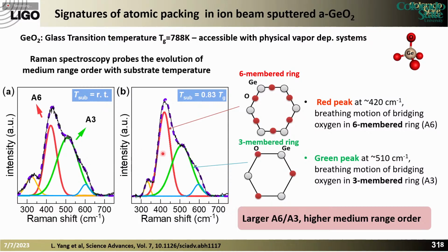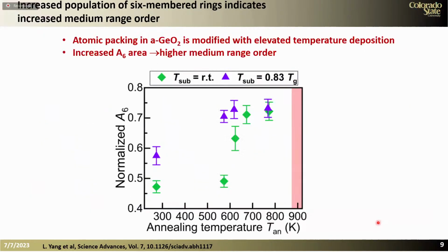And we investigated how this population evolved when we either deposited the material at different temperatures or when we also annealed. And actually, this has led us to identify that, number one, by sputtering, we can form glasses that have a high degree of stability, and we see that by looking at an increase in the population of the 6-member rings. So this larger A6 over A3 ratio indicates a higher medium range order, and that is a sign of stability.